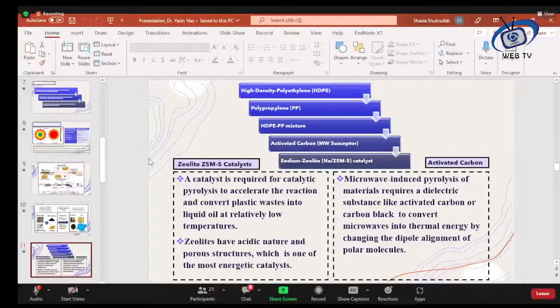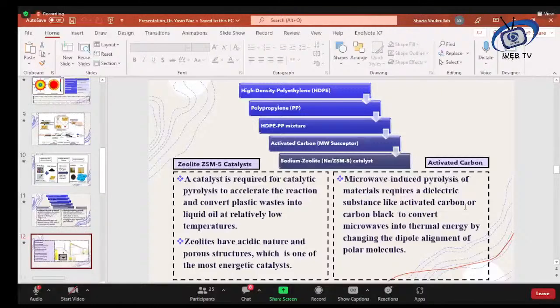As I mentioned, we use zeolite, ZSM5 catalyst type, and activated carbon because it is the best material. It has a high dielectric loss factor as compared to other materials. So it is the best intermediate to transfer the heat from microwave to the plastic.